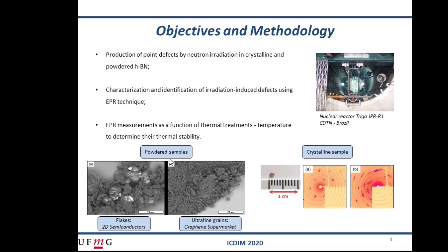Three samples were used in this work. Two of them are powdered samples. One of them is a flake from 2D Semiconductors, and another sample is ultrafine grains commercialized by Graphene Supermarket. Both samples are very similar in EPR measurements. And the third sample is a crystal, here, a little crystal, but this crystal has a problem. Only its Z direction is well defined. Its hexagonal layers of boron and nitrogen are well stacked, but they are twisted randomly around this stacked direction, which gives this distorted representation of the reciprocal lattice of the material.